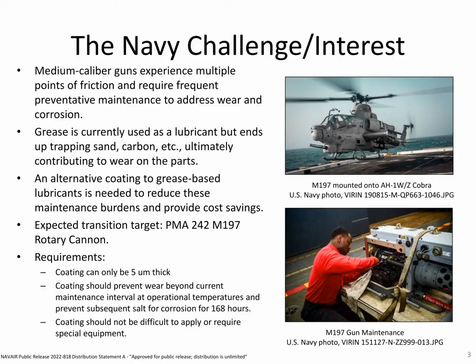The challenge in this project is to develop a very thin, solid coating for various types of steel that provides corrosion protection and wear resistance to the part. Medium caliber guns, such as the M197, which is shown in the picture on the right, mounted on the Cobra helicopter, experience a lot of friction. They're currently lubricated with grease, but the problem with grease is that it ends up trapping a lot of sand, carbon, basically making little ball bearings that eventually erode the part.